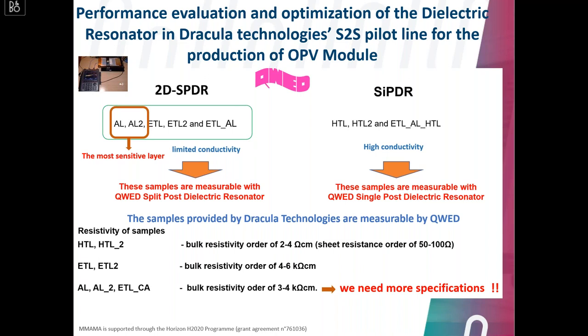And we can clearly see that, if we take the example of the active layer, we obtained a high resistivity, on the order of several kilo ohm centimeter for this layer, which is somehow consistent with what was already observed for similar materials. So for that we concluded that this technique is able to give us important information in order to evaluate the quality and the performance of our OPV devices.